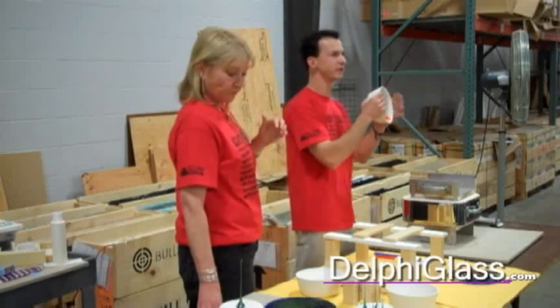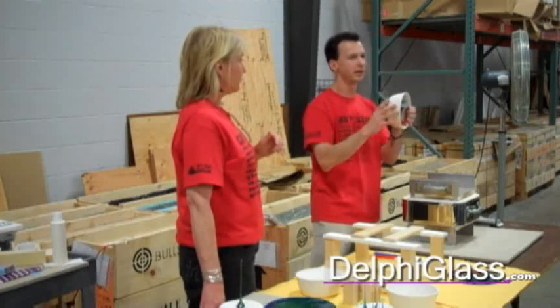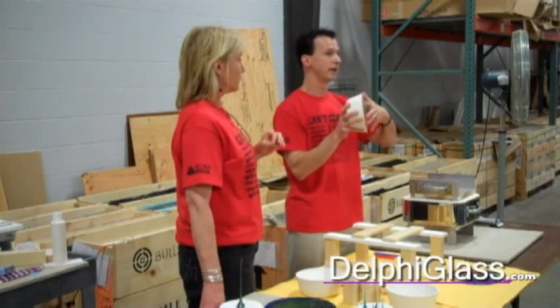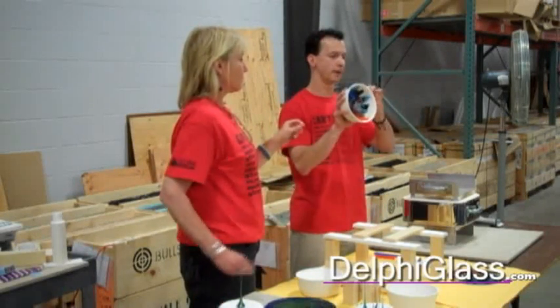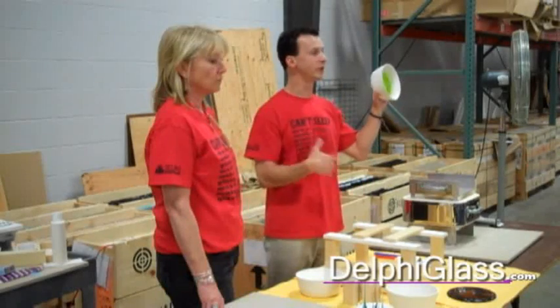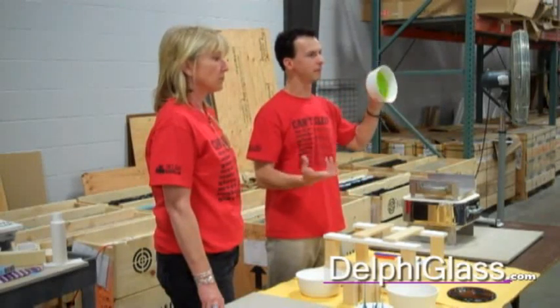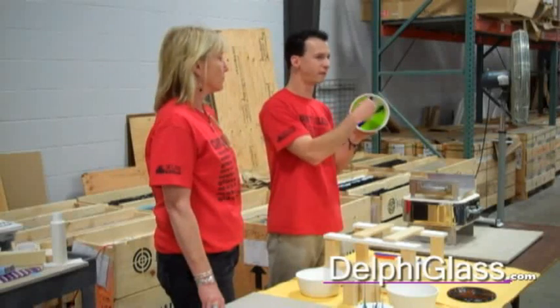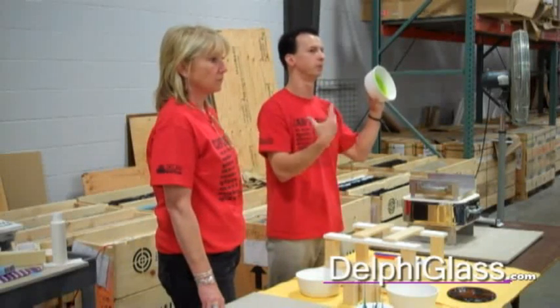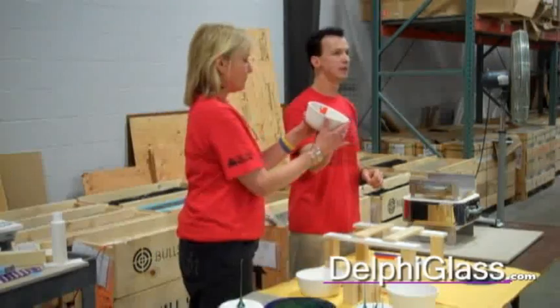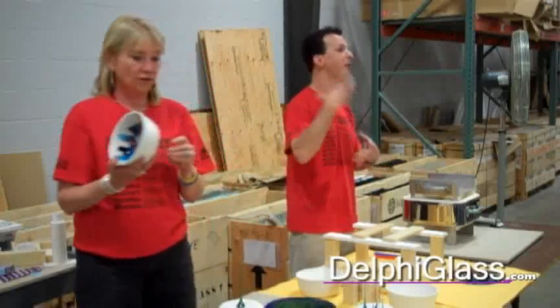It's the difference of coefficients of expansion between the glass and the ceramic, right? So if you have a lot of glass in there, it can be enough to cause the ceramic to crack. And these are reusable, but the problem is that if you put more glass in this and then fire it, it's going to have a little green and a little blue residue with it. So the key is to try to get as much of the glass out of the pot as you can while you're running it.